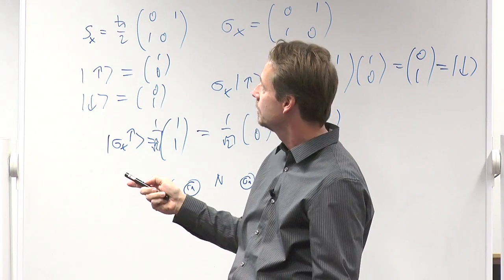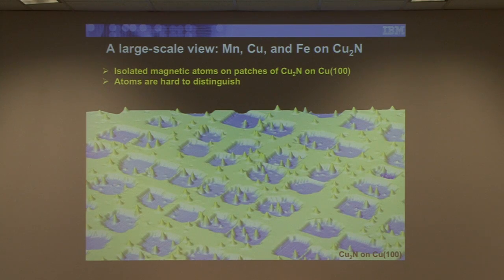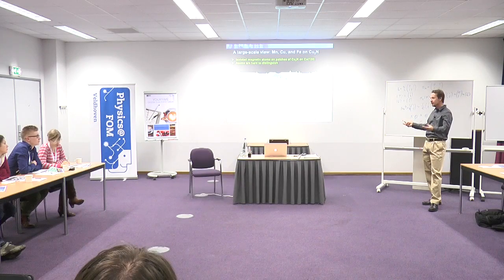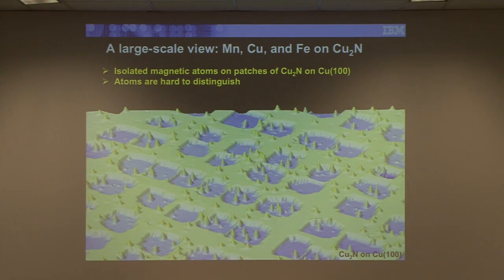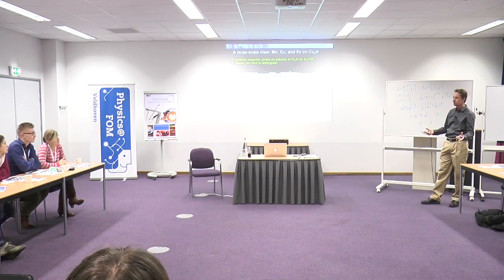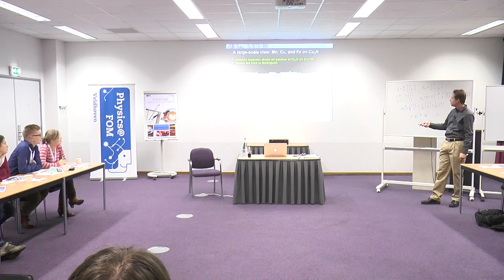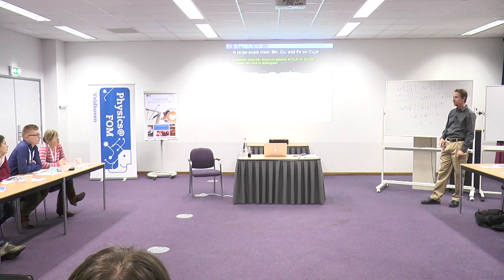So what we do is, before we do something that's complicated like this, we only use one metal atom, let's say manganese, and we look at the surface, and we look at the spectrum, which I'll show you in the next slide, for all the different bumps, like 100 different ones, and of those, maybe 95 will look the same. And 5 of them are close enough to defects that they will look different. So we just say, all right, most likely, this spectrum belongs to a manganese atom.